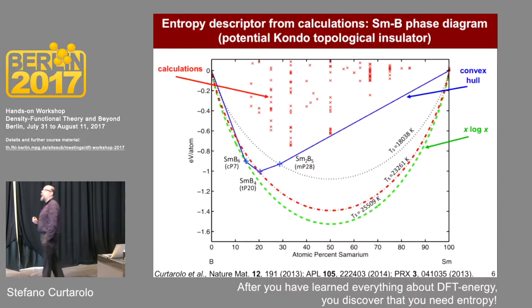So my idea was, wow, there is something going on with entropy. And remember, it's not just entropy S, the real keyword is T times S, which is the heat. So I tried to give a descriptor of the amount of heat that a system can absorb. Remember that you have all this gas. Even at low temperature, this gas is very mobile, so it has a lot of translational entropy, because the atoms can be here, here, here, here. So it's completely delocalized. So there is a lot of TS, even if T is low, S is very big, so there is a lot of delta Q. We try to capture this delta Q in these phases.